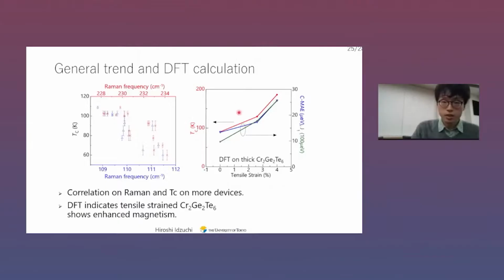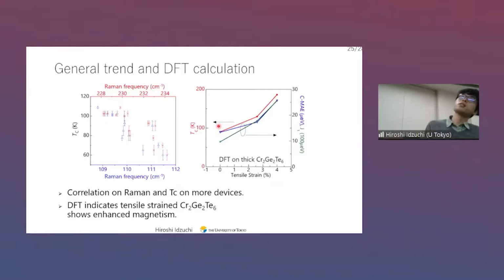You mean the DFT calculation or magnetism? Yes. Does it change the chromium-chromium distances, or the chromium-chromium angle? How does it change? Okay, I think it looks more at the distance itself. In this kind of compound, between chromium, there is a large antiferromagnetic exchange energy that decreases quite fast with increasing distance. So we think that is the reason why we see the increase.